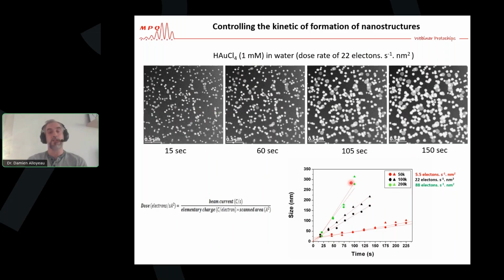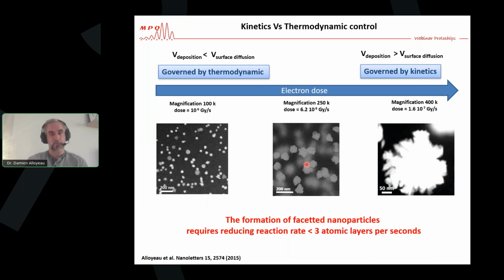So now we have a way to see the effect of the growth speed on the shape of the nanostructures. And here is the result. When you are at low dose rate, so low growth speed, you observe these well-faceted nanoparticles. Have you seen the growth mechanisms in the previous slides? And here you have those well-faceted nanoparticles because you are governed by thermodynamics, meaning that the deposition rate is much lower than the surface diffusion rate. So you are dominated by surface diffusion, and you give enough time to the system to reconstruct those well-faceted nanoparticles.